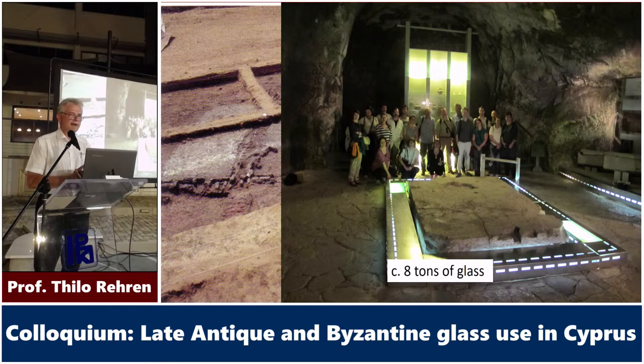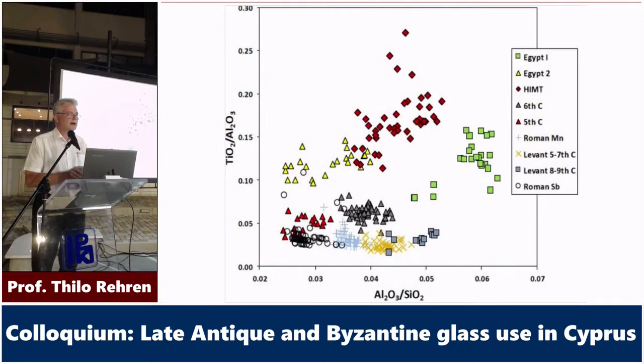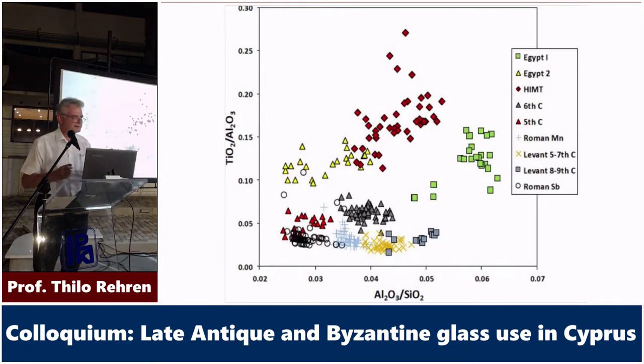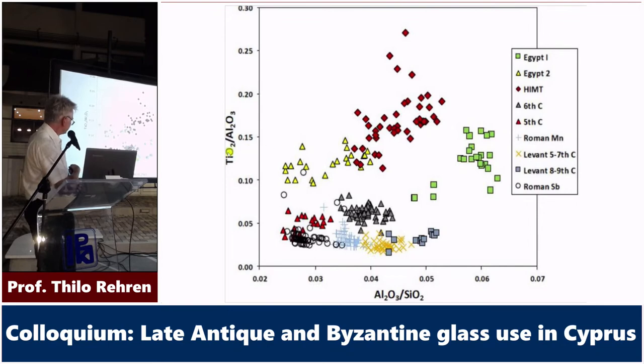So, if we take any of those glass finds now and look at that chemically, they're all soda lime silica glass, but it's the spices that differ, the trace elements, the minor oxides, and they allow us, if we look at, say, titanium versus aluminium, or aluminium versus silica, to differentiate different producers of glass, because each producing kiln site, furnace site, was using their local sand, and their local sand is different from the sand of the neighbor. So that signature of minor oxides in the sand stays in the glass, and then you can say, oh, that's a glass from that company, and this is a glass from another company.